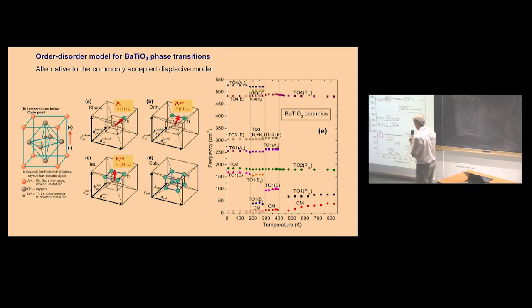So in this case, when you have structure phase transition to tetragonal phase, the soft phonon splits. Here is one component, and here is another one. It is along c-axis. This is in AB plane. There is huge splitting, which is also responsible for much lower permittivity in C direction.